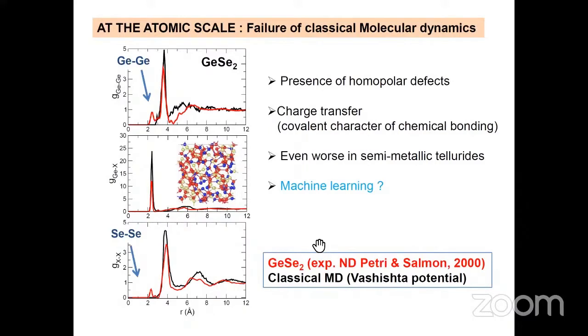So we want to probe those materials using ab initio MD. So first, maybe I should remind that on the atomic scale, you cannot use classical molecular dynamics using a force field. And this becomes already obvious if you look at a very simple GeSe2 system, because if you compare the results that you would get from a classical force field, like for example, here the Vashishta potential, which is very well known in the literature, and you compare it with results from partial correlation functions accessed from isotopic neutron diffraction, you can see that the simulation completely fails to reproduce typical homopolar peaks that appear in the GeGe partials and in the selenium partial, that is here in red.